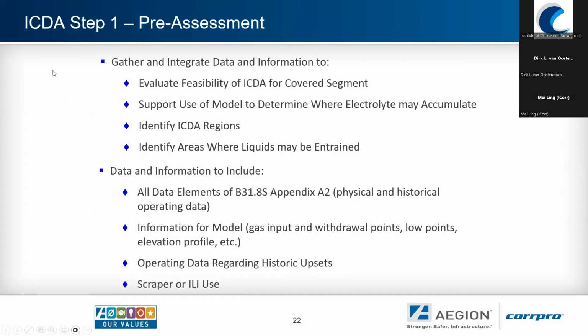So the pre-assessment phase here is gathering the data, making sure that the ICDA process is feasible and applicable, and then begin to start to look at the modeling that's going to be required in order to determine the movement of the electrolyte and water in the pipeline, identify the specific regions along the pipeline where internal corrosion could be a concern, and then compare that with these high consequence areas. Look at the accumulation point or where entrainment may be taking place.